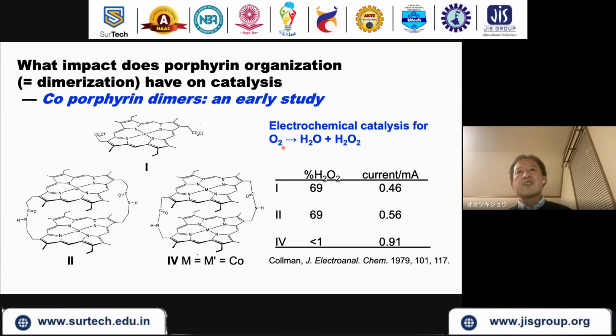So oxygen reduction, if you do 4 electron reduction, you get H2O, but if you do 2 electron reduction, you get hydrogen peroxide. So the selectivity of these catalysts is important, and this is the selectivity of producing hydrogen peroxide, and this is the current. So for the monomer, percent H2O2 is 69%, very high, and the current is 0.46.